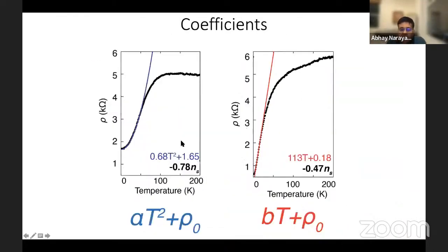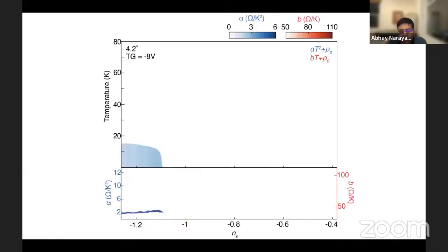Now, one of the classic signatures of quantum criticality in, say, the heavy fermion systems is obtained by looking at these coefficients of the temperature dependence of resistivity. So let's look at the T-squared coefficient and the T-linear coefficient at different points in this phase diagram. If I'm very far from this half-filling point, then I see that this coefficient of T-squared behavior is more or less a constant.